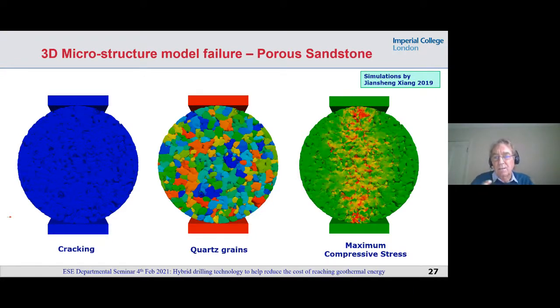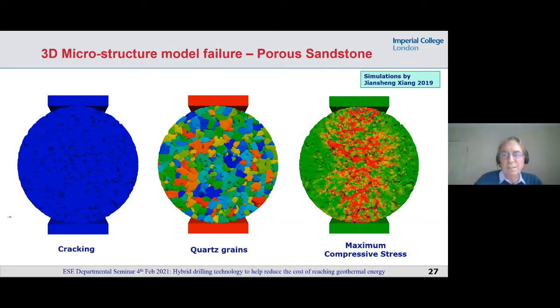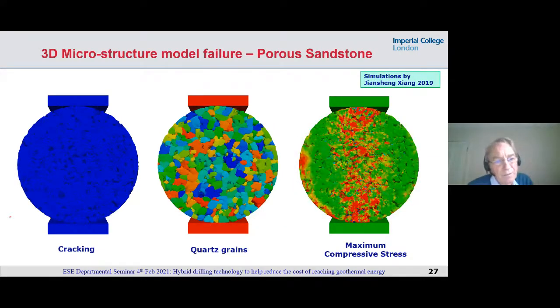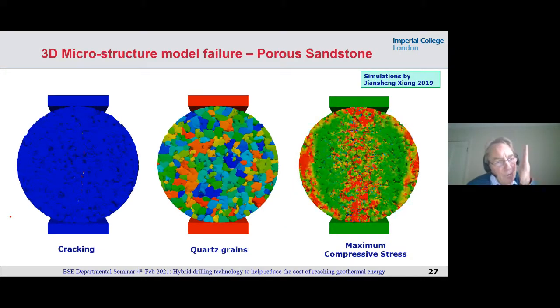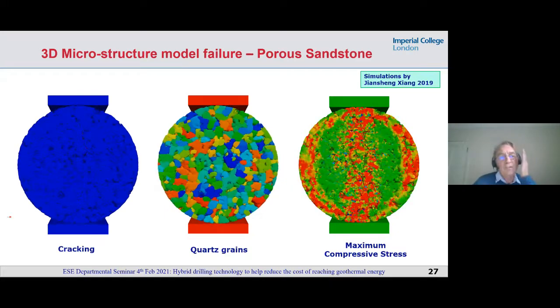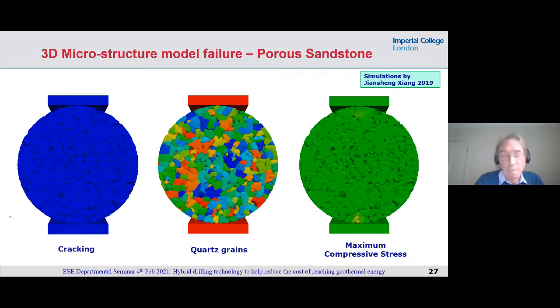You can see that the compressive stresses are building up. After it's failed, they move to the side and take up stresses around the outer arc. And on the left-hand side, you can see the crack breaking through to the front face, and actually it's a nice straight crack, as I was predicting and suggesting.